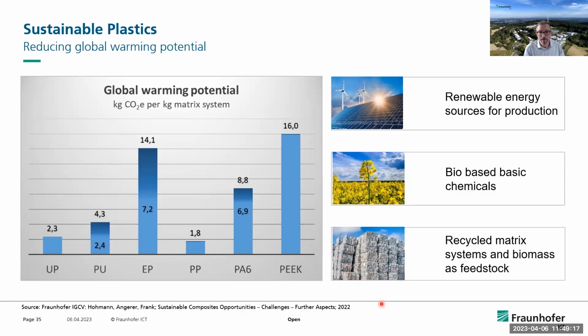Deep inside a complex topic when we look into the matrix system. What you can see here in the diagram is the global warming potential caused by the production of 1 kilogram of resin. First, what you can see here is that especially the high-performance matrix systems can cause quite a bit of global warming potential of up to 16 kilograms CO2 per kilogram.